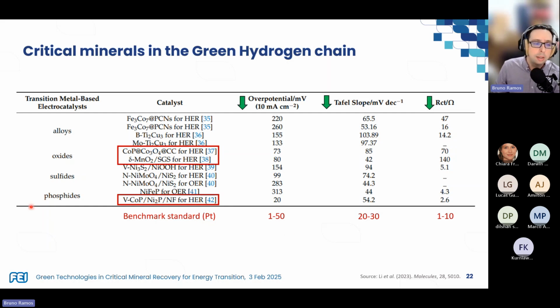So this paper here, published last year, 2 years ago, 2023, I still have to get used to that. It shows some of the key materials being proposed to be worked on in electrocatalysis to produce hydrogen. And here we have different classes of materials: alloys, oxides, sulfides, and phosphides, and three parameters: overpotential, Tafel slope, and the resistance. So overpotential means how much additional potential I have to supply to have this current happening, which means that the lower this number is, the less energy is required to make the electrolysis happen.